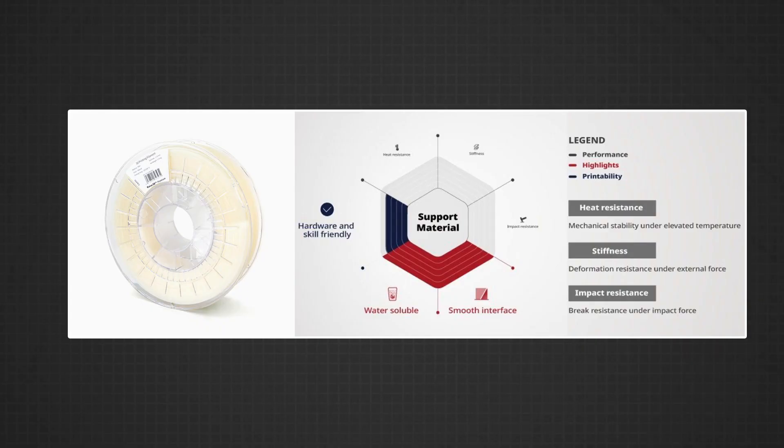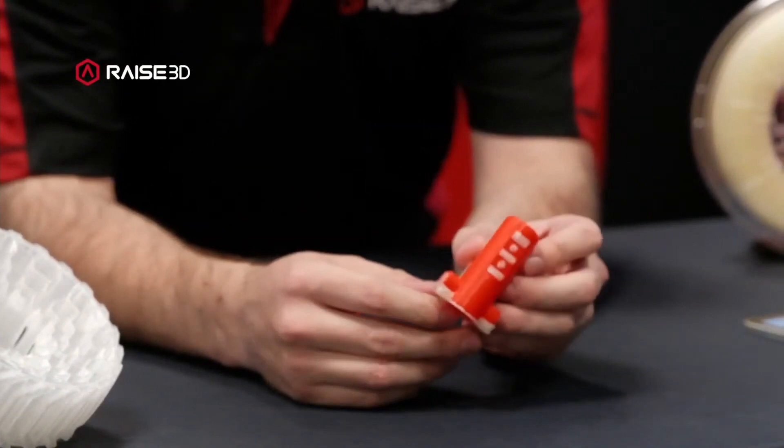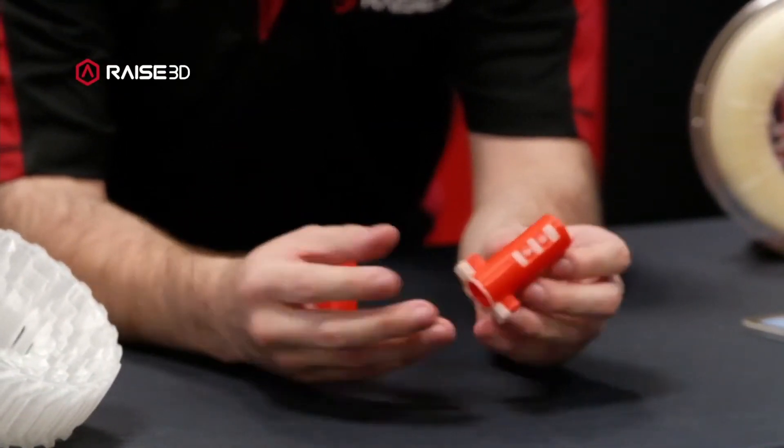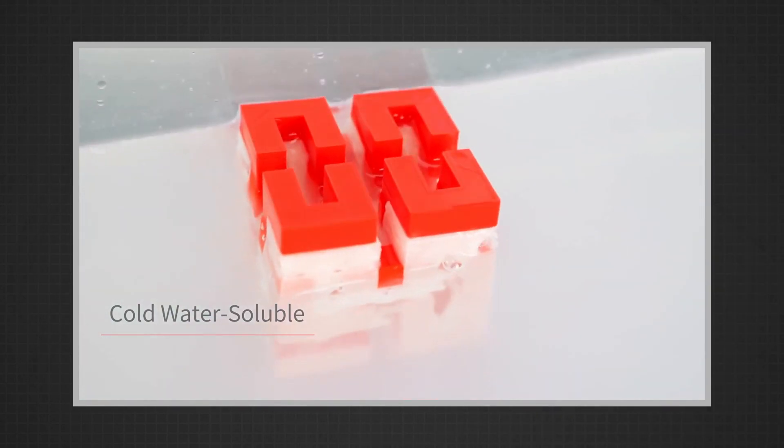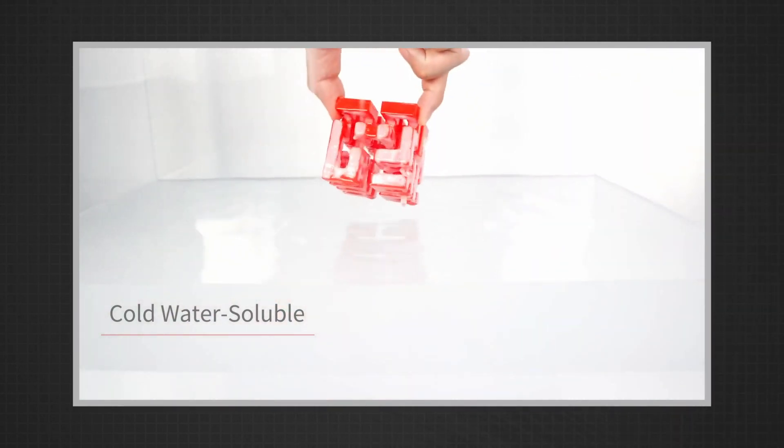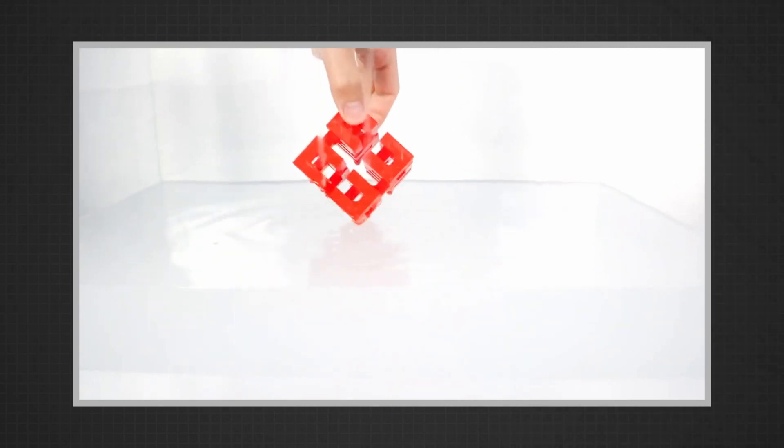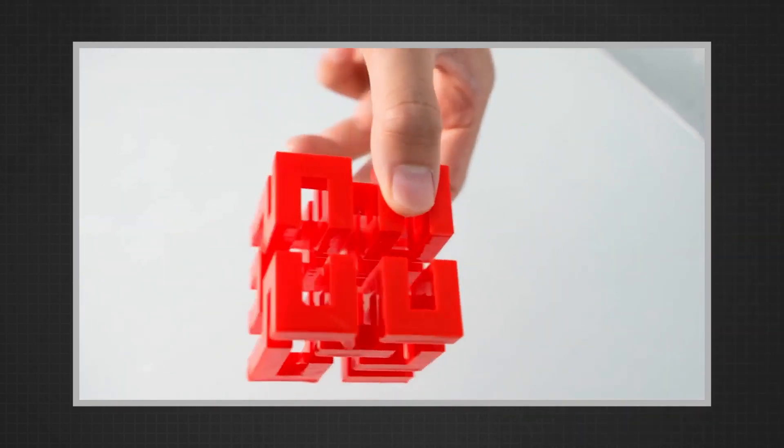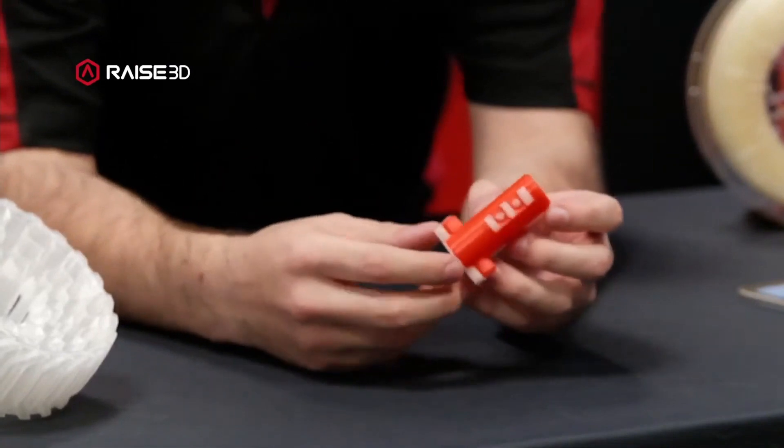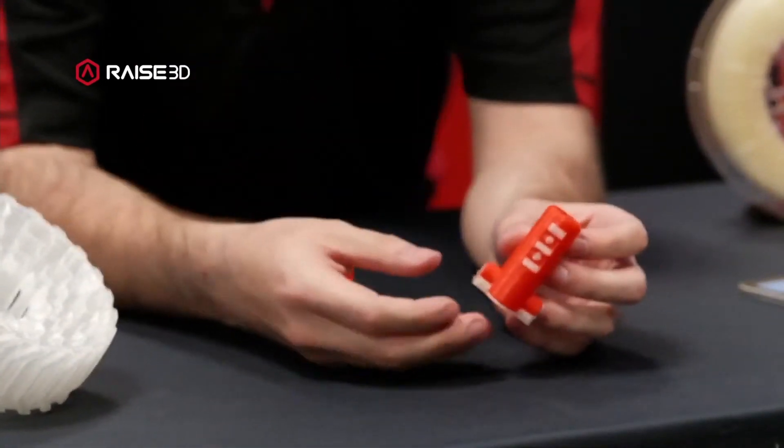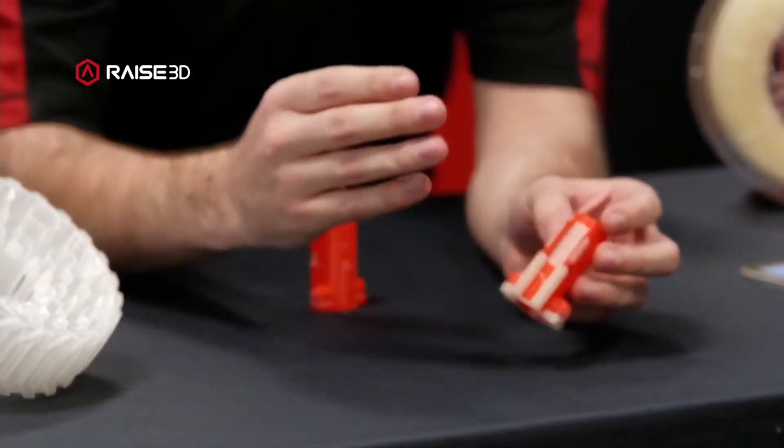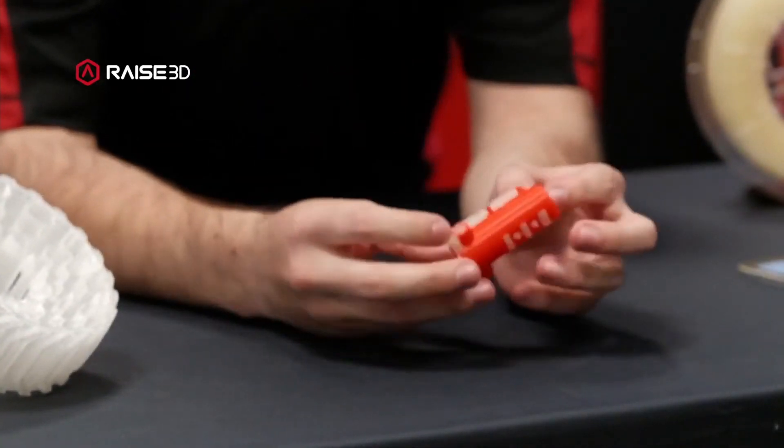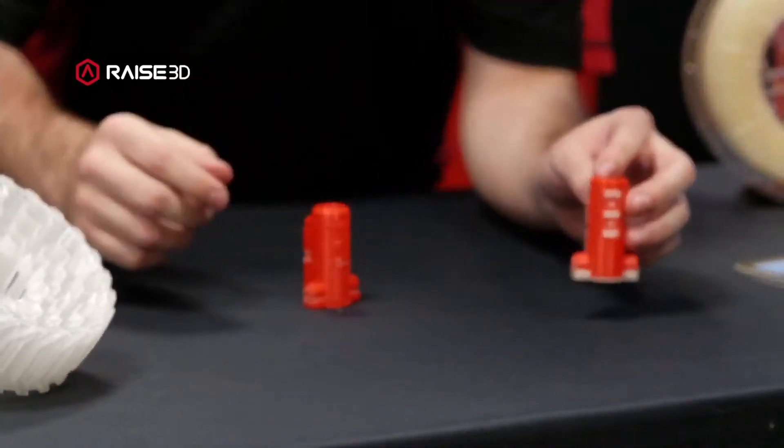The new PVA Plus that we have is still optimized for working with PLA materials, but it dissolves a bit quicker and a lot cleaner than the original PVA that we had. So when we were dissolving things before, it would get kind of gummy and might need to be washed a couple extra times. The new PVA Plus is formulated to dissolve faster and dissolve cleaner.